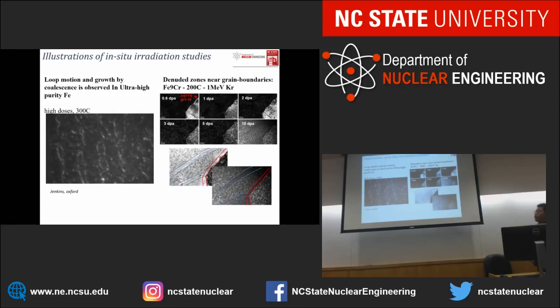Here on the right, this is another example: the in situ ion irradiation in iron-chromium model alloys. As you can see, the in situ experiments allow us to take pictures of the same area at different doses. By comparing those pictures, we can identify the evolution of the microstructure. Another thing we can show here is, within the grains, the defects created by irradiation are homogeneously distributed, but near the grain boundaries, there are some dislocation denuded zones. That's because grain boundaries are considered perfect defect sinks, which absorb the defects and create the denuded zones.